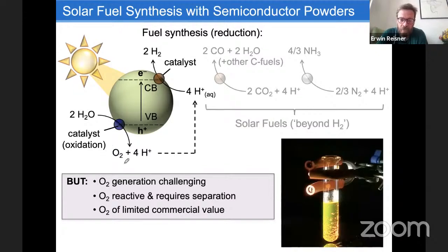And then if you manage to achieve it, you form actually quite a reactive molecule in your system. If you look at this picture here on the right, which is a photocatalytic system where we just shine light on a solution and some hydrogen bubbles form, and you co-evolve some oxygen, of course you form a Knallgas, which is not ideal. So you have immediately an explosive mixture. But reactive also means it can easily start forming a short circuit. This oxygen can just diffuse to the reductive side and reduce oxygen instead of protons, which leads to inefficiencies. And when it does so, it often forms oxygen radical species, which again can decompose the catalytic process overall. And again, with the Knallgas, you need separation.